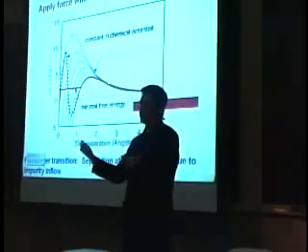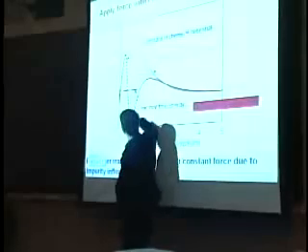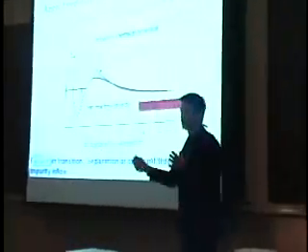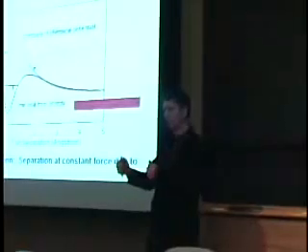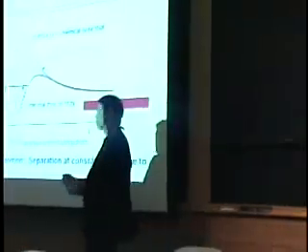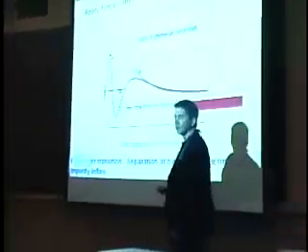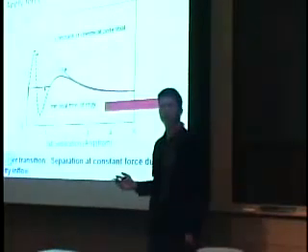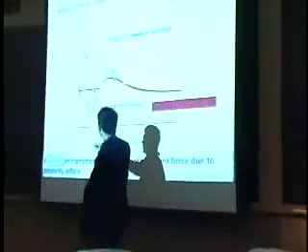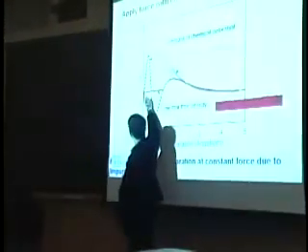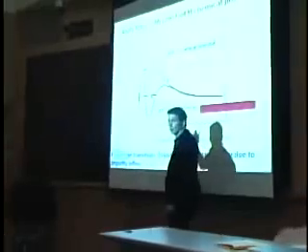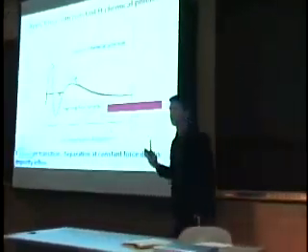It sort of makes sense. As you pull, the force goes up, no surprise, and then you reach a critical point, the point of maximum force. At that point, you're unstable, because as you pull further the force goes down. On the downslope, you're essentially unstable. But look at the red line. This is a chemically equilibrated system, and it behaves very differently. Essentially, you pull a little bit, you open the crack a little bit, and then the crack opens with no increase in force. Okay?